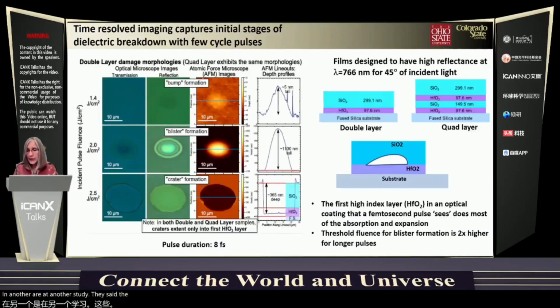In another study, we investigated the mechanisms that give rise to damage in these coatings at ultra short pulse. These are single cycle pulses of duration of 8 femtoseconds. And what we learned from these time resolved images is that prior to damage, there is actually a blister formation that is reversible with fluence, and that occurs at the interface between the first hafnium layer that is deposited below the top silica layer. And so these results suggest that, again, interfaces are very important, and also stress is very important.